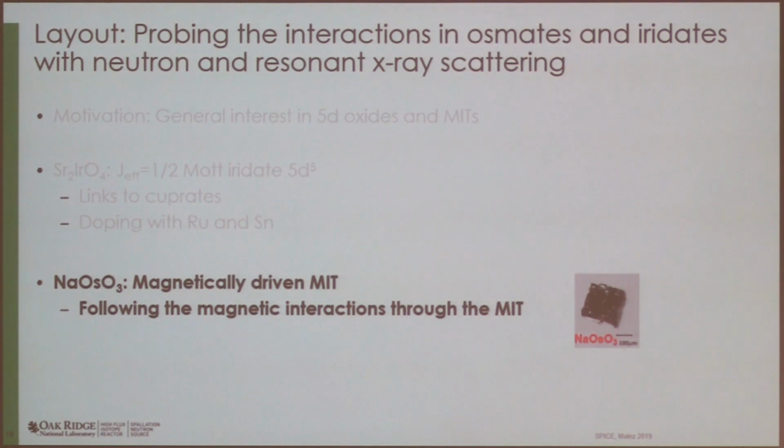Iridium has no single-ion anisotropy with J equals 1/2, but ruthenium is spin 1, so it may have single-ion anisotropy. Is it because of that? It may well be, yeah. I'm not sure. To model the data, we just put in a single-ion anisotropy and then fit the exchange constant, which is 42. It's very large. Yeah. Really the same number practically. Okay.